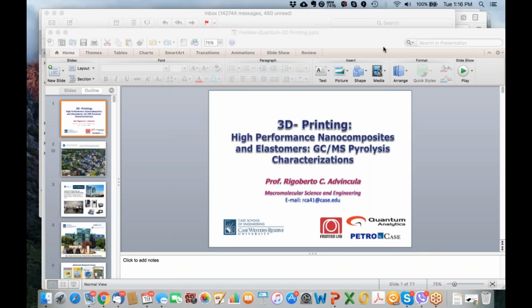So that technique is more dependent upon relative heat capacities and heat transfer properties. And then the final technique that's used is based on a Curie point. Essentially the sample is wrapped into a foil that can be heated by an RF frequency, and it's much like the filament in that the device is energized and the foil is heated up to its Curie point, at which it stops, and it remains at the temperature that is a property of that Curie point of that particular foil. So in that case, you would then use a different foil for each particular temperature that you wanted to achieve. So those are the three basic modes of use.